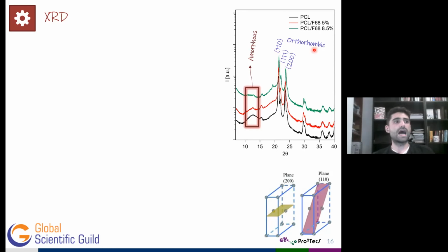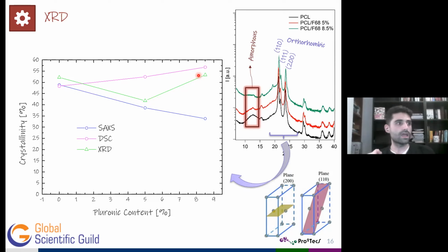Well, from these patterns, we also evaluated the crystallinity degree. And as we can see from the green line, which corresponds to the XRD test, there is generally a good agreement with the DSC test, indicating that all the crystals present in this polymer, in the blends or in the pure compound, have the same orthorhombic conformation. Indeed, only the system with the lowest pluronic content deviates from that trend, but it is worth mentioning that this system has a large heterogeneity that may lead to inconsistent behavior when conducting this kind of test. We have so many different values resulting from this test, but we just took one of them.